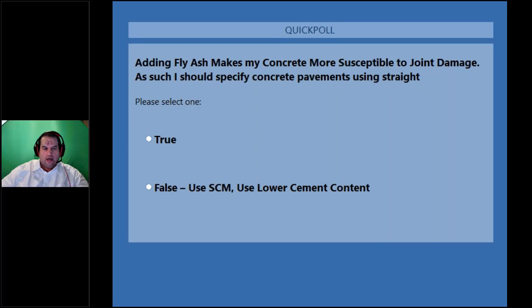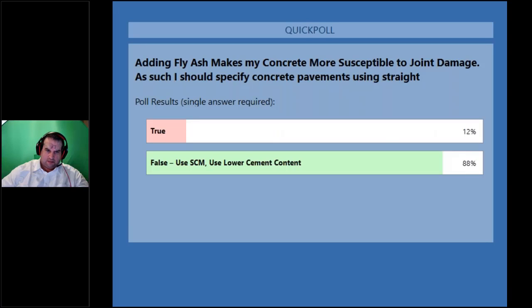Well, hopefully now we've seen that fly ash actually makes things better. So the whole idea is we want to use more SCMs, use lower cement content, and this actually makes our concrete much more durable. So this statement is completely false. And in fact, fly ash doesn't make our concrete more susceptible to damage, it makes it less susceptible to damage, right? Straight cement mixtures are the most prone to these types of damage that we can have.